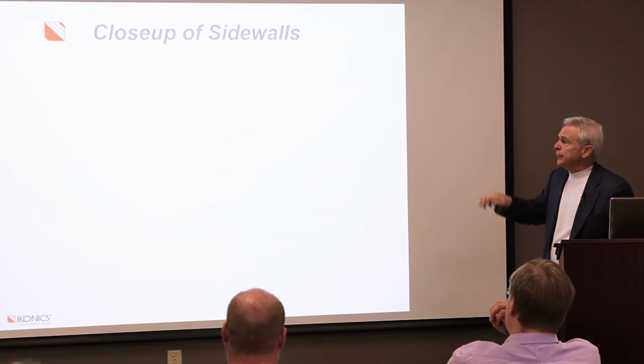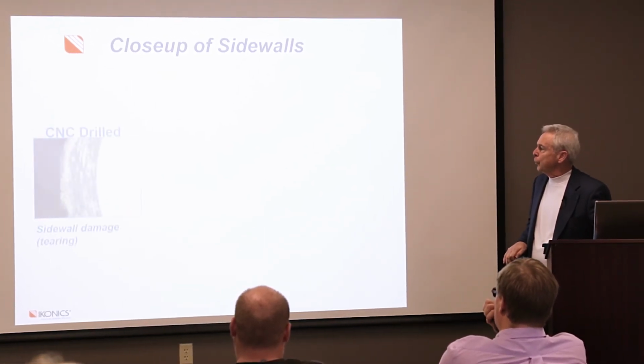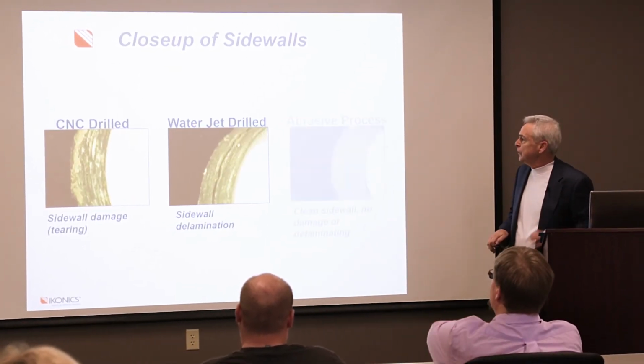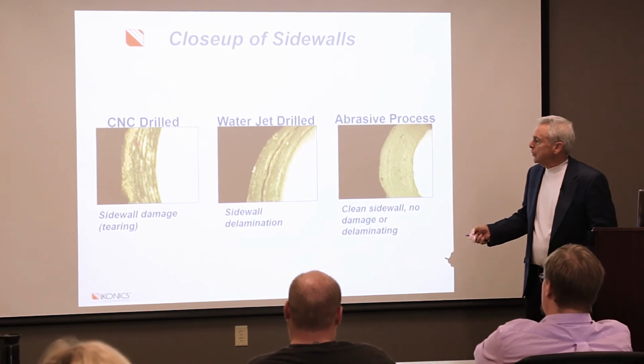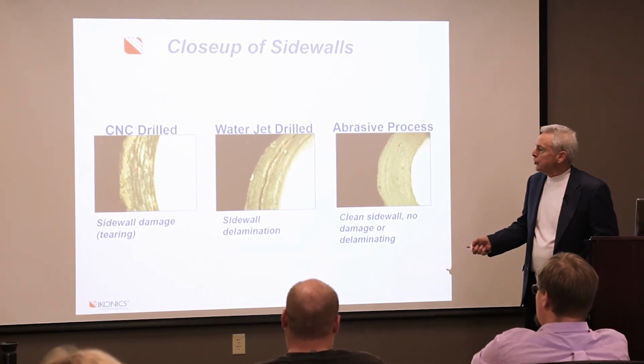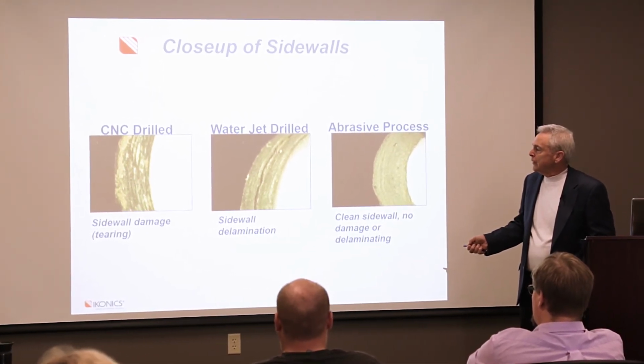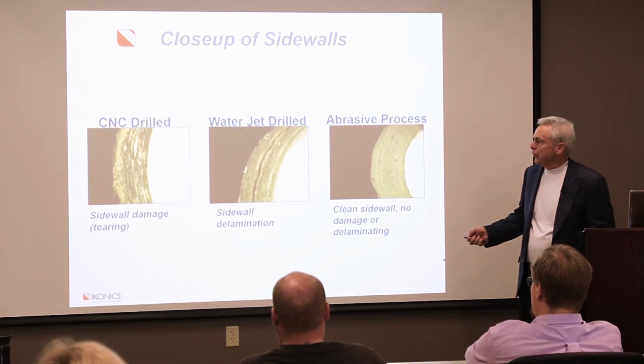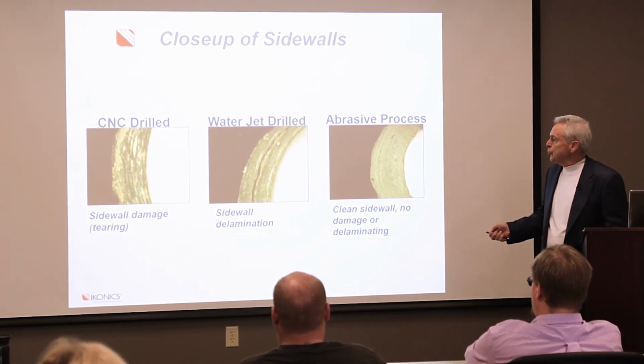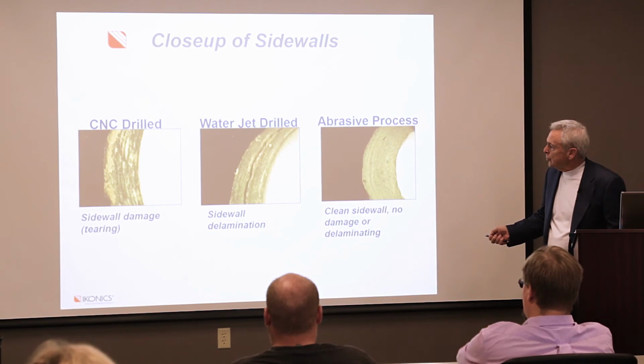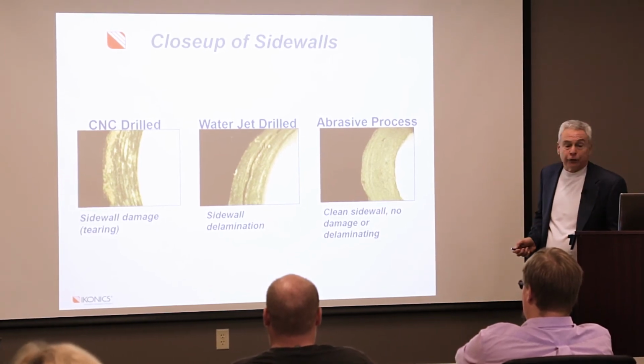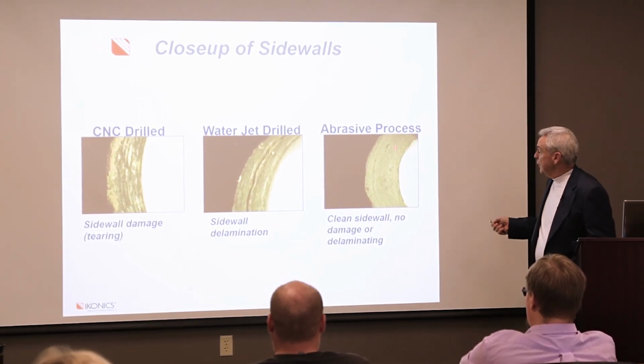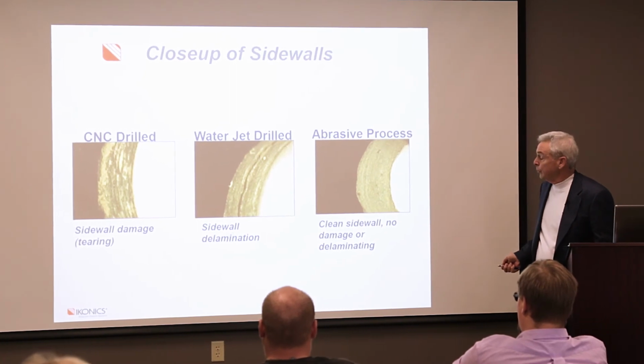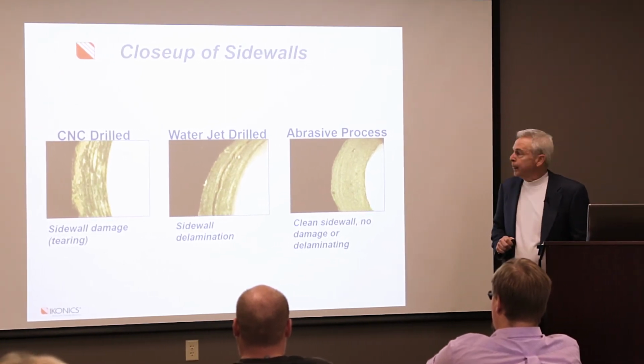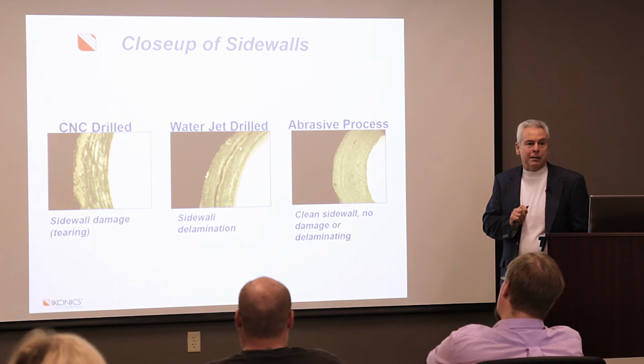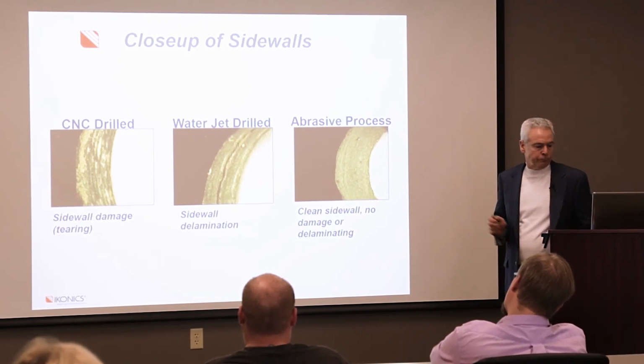And the way to illustrate that best is to actually look at, I'm going to put all three of these up at the same time because it's easier to show you. If you look at CNC drilling, and you look at a cross-section of the sidewall, you can see the kind of damage that occurs there, the tearing that occurs with drilling. And with water jet, you can actually see delamination occurring between the layers. Okay. However, the abrasive process shows all the sidewalls are clean. That's a big plus, and the aerospace people like that.